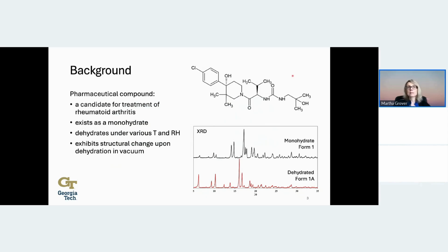And the compound existed as a monohydrate as provided to us by BMS. But it was observed that it can dehydrate under relatively mild, ambient temperature and relative humidity. And so we can see the XRD pattern, X-ray diffraction pattern, associated with the original monohydrate form, which we're going to refer to as form 1 here. And then after being in a vacuum at ambient temperature, it would become dehydrated. So we can see that there are some very different qualitative features associated with the dehydrated version, which we're going to refer to as form 1A.